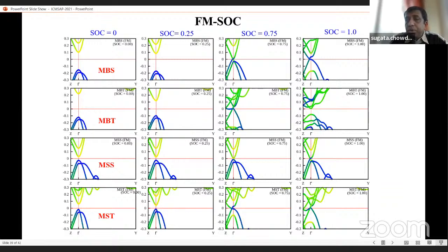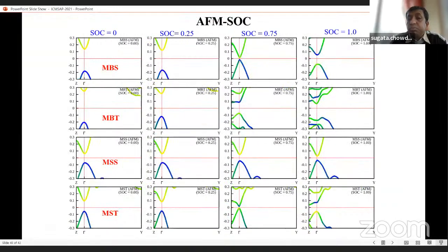And the most important part here, I would like to mention, is that, I'm sorry, I did not present that slide here, but the manganese bismuth selenide phase transition temperature is around 50 Kelvin. On the other hand, for the manganese bismuth telluride system, the phase transition temperature is actually 25 Kelvin. So we can say that we are getting a higher temperature, and this could be a very good candidate for that. And the second thing is that we also look